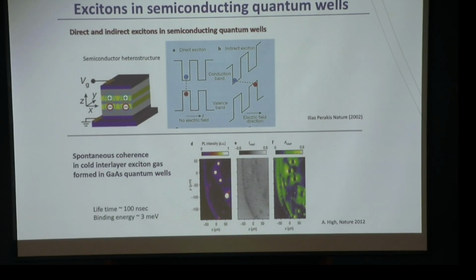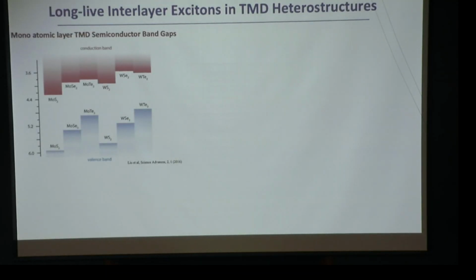Part of the reason is that the exciton is still kind of short-lived, because the quantum well in this semiconductor is not binding the electron strongly enough, and it is leaking out the electron, causing recombination. And also, the strong dielectric constant of the semiconductor screens the exciton, making the binding small. Right? So this experiment can only be run at very low temperature. Of course, here comes the 2D system as one of the rescues.